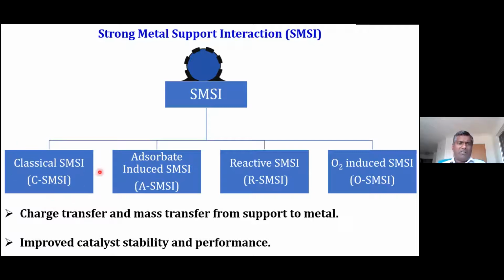It's pretty much well known. But there are a few other kinds of SMSI, which are adsorbate induced SMSI, reactive SMSI, and oxygen induced SMSI. These are relatively less known in the literature, and active research is being carried out recently on these kinds of strong metal support interactions. What are the features of this SMSI? The charge transfer between metal nanoparticle and the support, and mass transfer from the support to the metal. Because of the mass transport, the oxide layer covers the metal nanoparticle. Because of this, the catalyst can have improved stability and sometimes better performance.